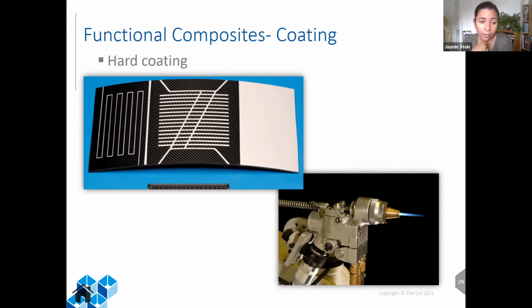And another advantage is this can be used for different things. But you can also use it in a composite as a primer, for example, where the pull-off load is about 12 megapascal. So it's quite high. Apparently, a standard primer or paint is about 4 megapascal. So the pull-off strength is very high. So what people at the moment are using is for lightning strike protection, and also for where the patterns are, we can also use it for different type of materials.